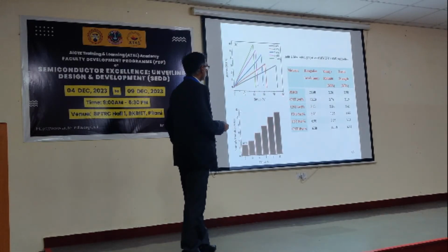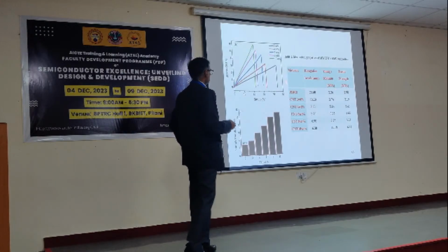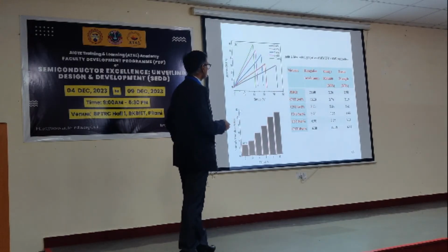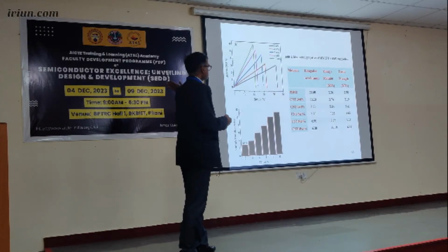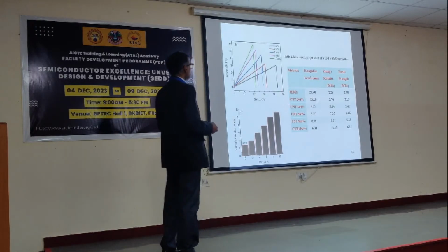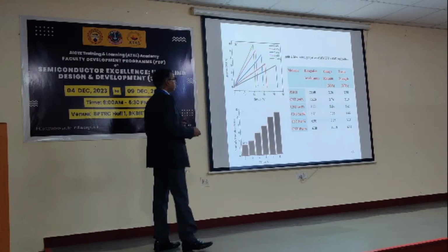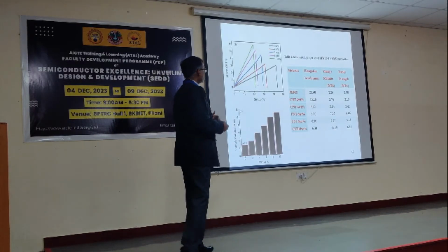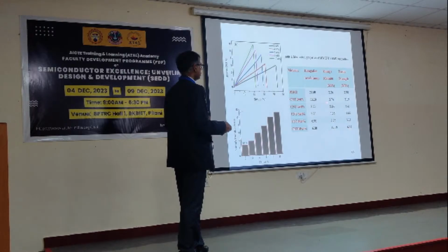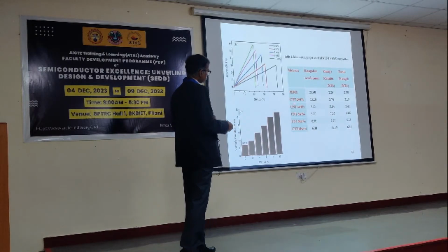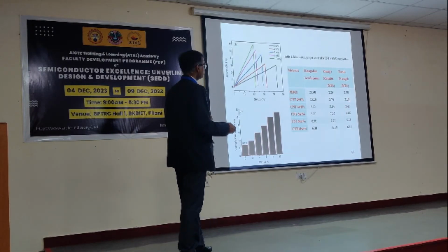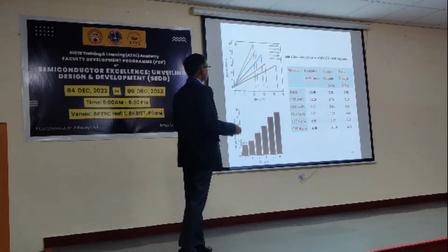So you can see that with a simple PDMS, these are the properties for base to curing agent as 10:1, because that is already decided in previous testing that we have to take 10:1 PDMS. But in that we are actually coming up with the composites, so in what ratio you will be adding that is tested here. And you can see that when you increase the CNT level from 2 weight percent to 10 weight percent, your tensile strength is increasing and your young modulus is increasing and elongation at break is going down.